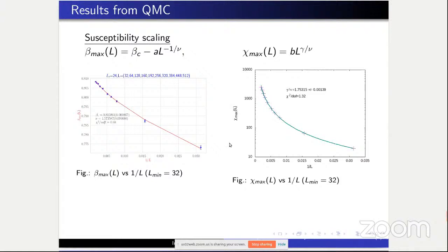So the position of the peak of the susceptibility, beta max corresponding to system size L, scales like this: beta C minus A L to the power minus 1 by nu. So we can fit the data corresponding to beta max L and get the value of the critical exponent nu and beta C. Similarly, we can fit the maximum value of susceptibility corresponding to various system sizes L, according to this scaling relation, and get the value of gamma by nu from the fit.